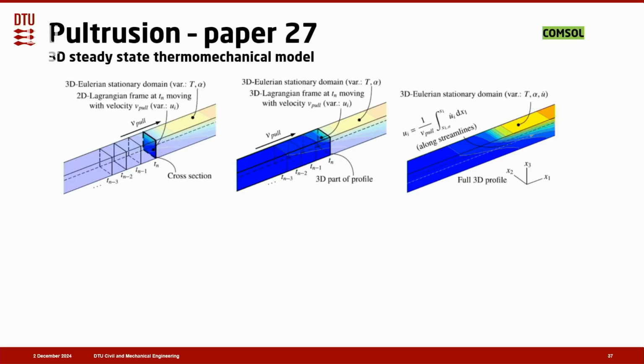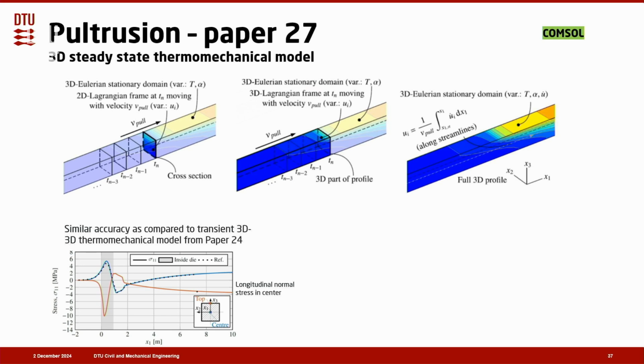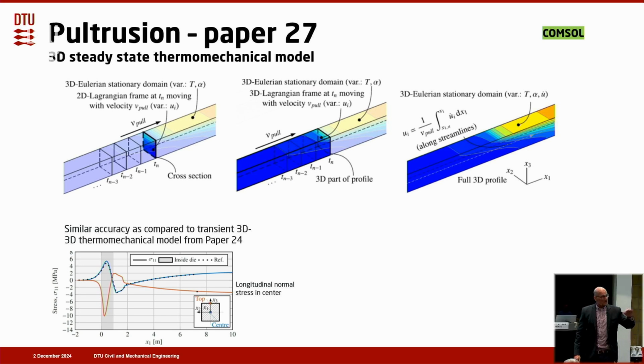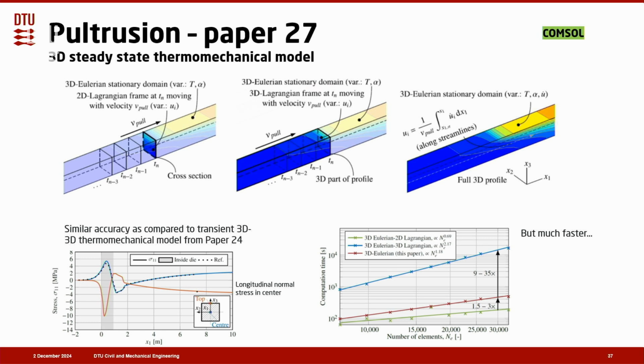So we were inspired by some people also from welding who did this before, and then we were integrating deformation rates along streamlines to get final deformations. And this model was actually showing the same accuracy as the 3D transient thermochemical mechanical model I showed before, but it was calculating much faster. So if you want this steady-state situation in pultrusion, and this is what you often want because it's a steady-state process, then you should definitely go for that. But if you have startup or stopping problems that you want to analyze, then of course a steady-state model is not sufficient.